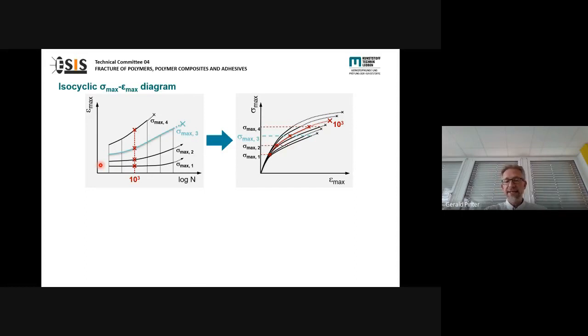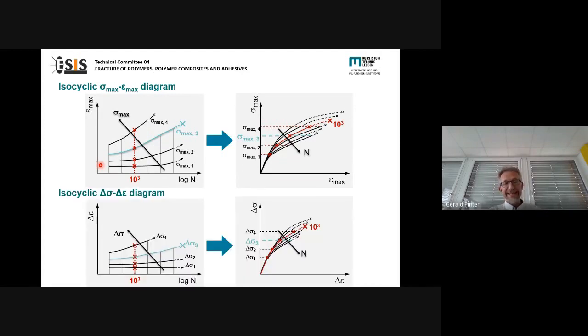And what we get in the end are stress strain diagrams related to the sigma max value for the different cycle numbers. And typically at higher cycle numbers, of course, the values are decreasing. So the material is getting softer and softer as a result, as already mentioned, of viscoelasticity and of damage. And again, looking here at the sigma max epsilon max diagram, similar to the secant modulus, this diagram covers viscoelasticity and damage. If we are plotting only the delta values, so the delta sigma delta epsilon values, like the slope in the dynamic modulus, we only get information about the damage in the material.